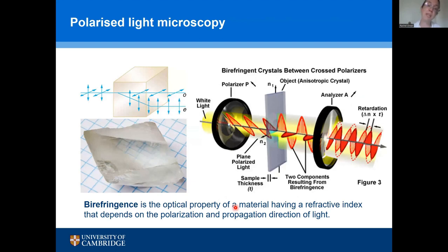Polarized light microscopy is a way of looking at birefringent materials, materials whose refractive index is different along two perpendicular directions. Essentially, in a classic polarized light microscopy experiment, which would be done in transmission, we have polarized light coming into our sample. Because of the birefringence, the difference in refractive index between the two optical axes, the axis of that polarized light is rotated somewhat by its passage through the material. That means that when the light meets the analyzer, it would be blocked if there had been no rotation, but because it has been rotated, light is able to come through, and we image those regions where there is anisotropy as being bright in our polarized light micrograph.